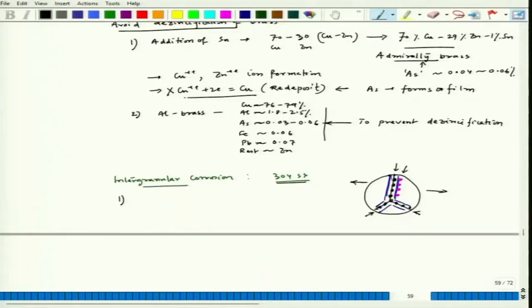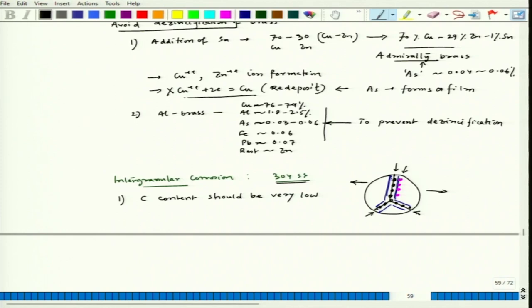If we look at it from a materials perspective, one approach is to keep carbon content very low. In 304, carbon content is about 0.08%. If we can reduce it to around 0.02 to 0.03%, there is not sufficient carbon for chromium carbide formation. This definitely avoids chromium carbide formation along the grain boundary and therefore prevents intergranular corrosion.